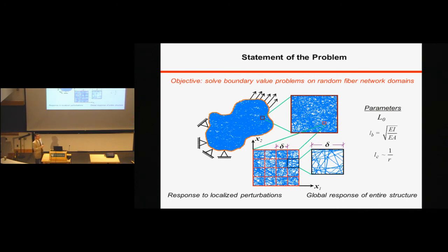On one hand, I know that I deposit fibers of a certain length. So that length is L0, the fiber length. However, when I deposit them down, I place a crosslink at each crossing point. So I divide the fibers into segments. What is the length of this segment? Well, it follows a Poisson distribution, and the mean of that distribution is called LC. It turns out that this parameter, LC, is actually inversely proportional to the density of the network, that is, total fiber length per unit area or per unit volume.